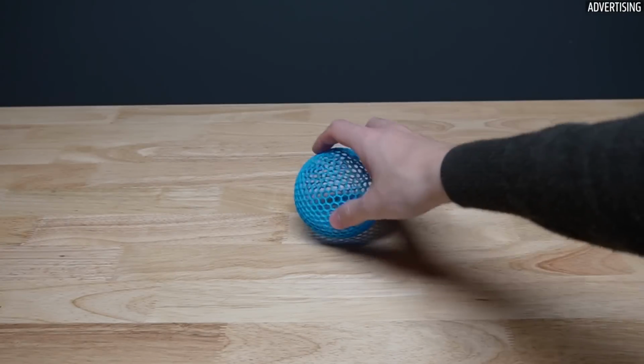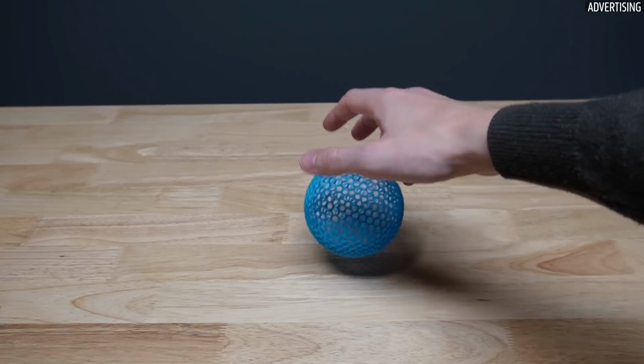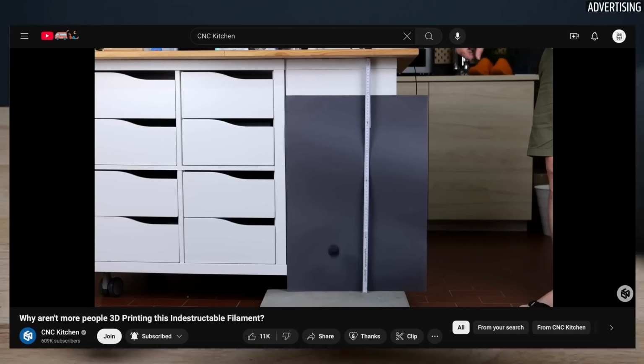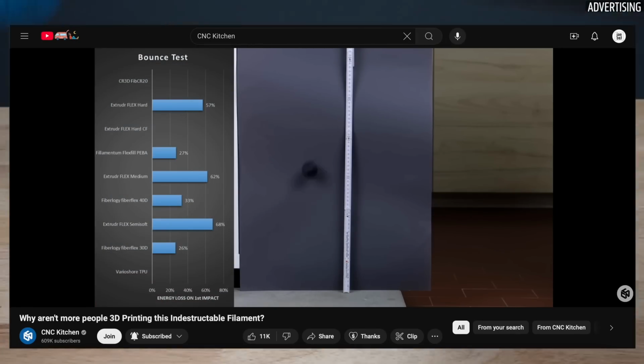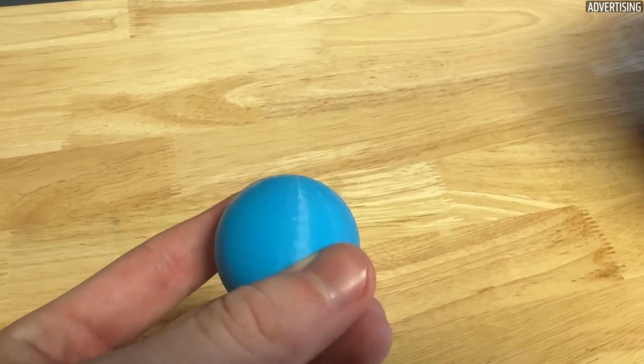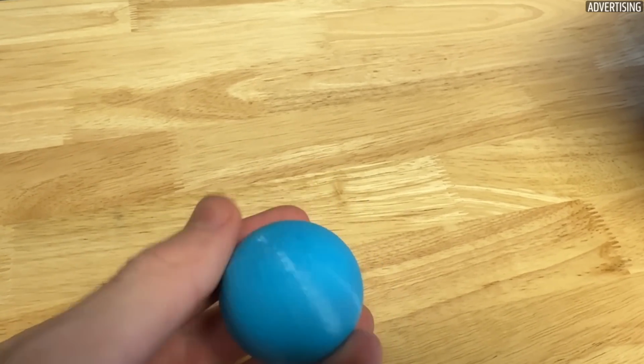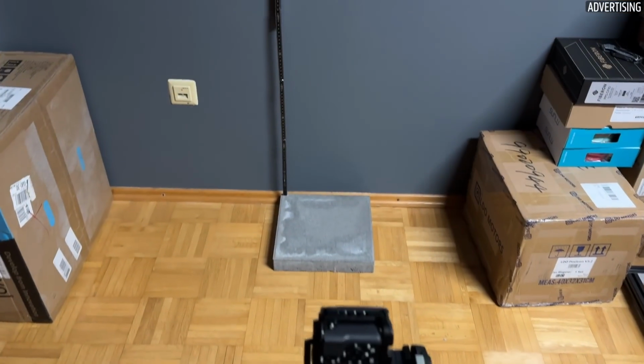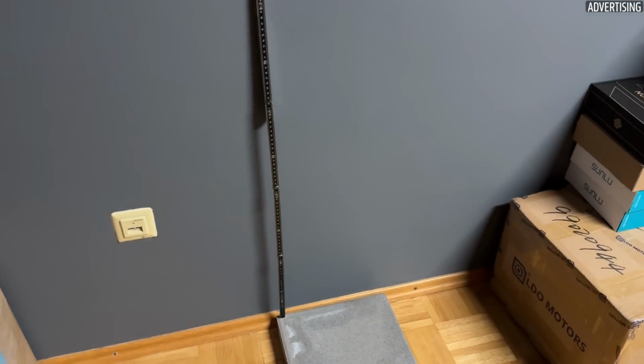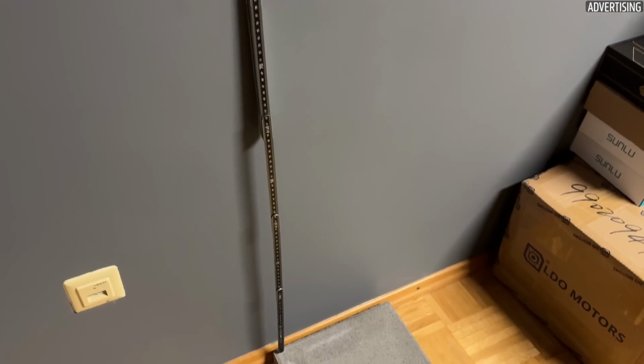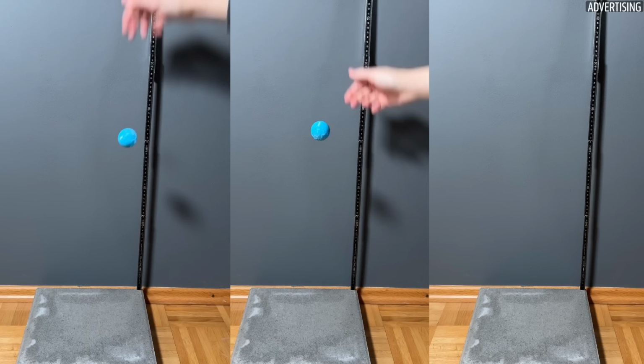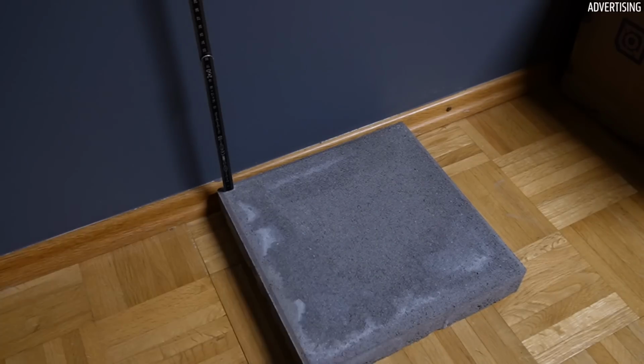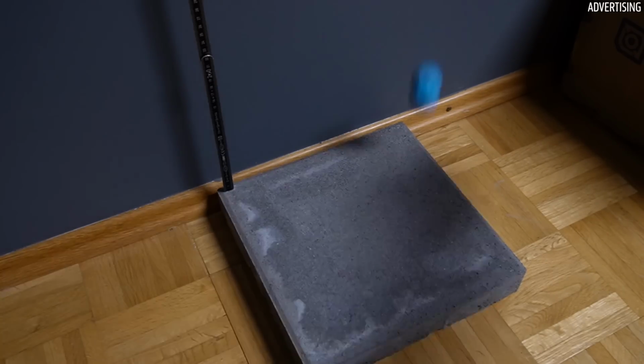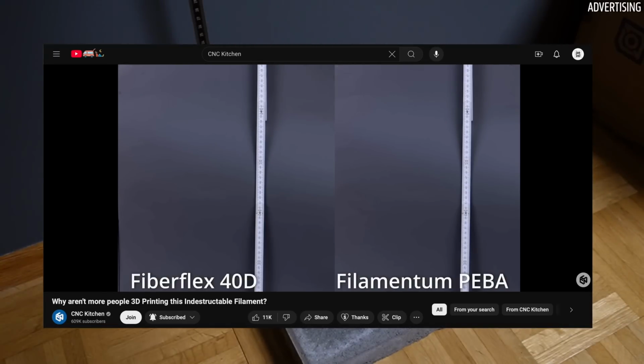When I asked myself how to measure and compare resilience, I remembered a recent video from CNC Kitchen in which Stefan used such balls. So I printed a sphere with a diameter of 40 millimeters and 15% gyroid infill from the PLA-HR and built a similar test stand. The sphere is dropped from a height of 80 centimeters onto a concrete slab. After 3 tests, I calculated an average absorbed energy of 35% on the first impact. Compared to Stefan's results with various TPU and TPE filaments, this is quite good, and only Peba and Fiberflex 40D were able to absorb even less energy.